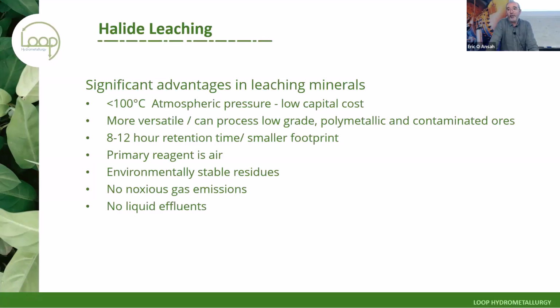The only thing that you can't do with our pregnant solution is touch it to anything ferrous. We used to joke that marine grade stainless steel that's made to deal with salt water, which is called marine grade 316 stainless steel, was named 316 because it would last 316 seconds in our process. In a pilot plant that we did a few years ago, we specified, of course, no wetted ferrous parts. A supplier missupplied a peristaltic pump with an inch thick stainless steel flange, and it lasted approximately 9 hours.